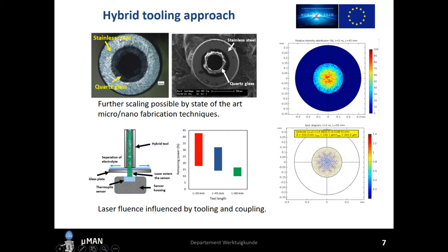So here we can see the tool is designed with an outer concentric layer of stainless steel and an inner concentric layer of quartz glass. We use quartz glass to separate the internal reflective surface of the tool from corrosion through contact with the electrolyte. We can also increase the acceptance angle of light into this tool electrode by means of this quartz glass. On the left we have an optical image, and on the right side we have an SEM micrograph of the developed tool.